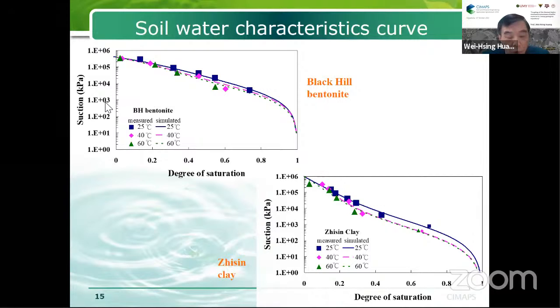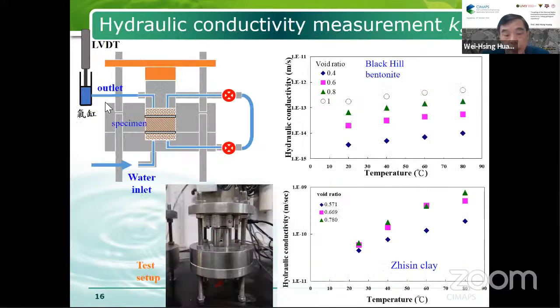The resulting soil water characteristic curves for Black Hill bentonite at elevated temperatures are shown. In general, soil suctions decrease with the increase in temperature. And the suctions of Black Hill bentonite are found to be higher than those of Zhisin clay due to its high plasticity.